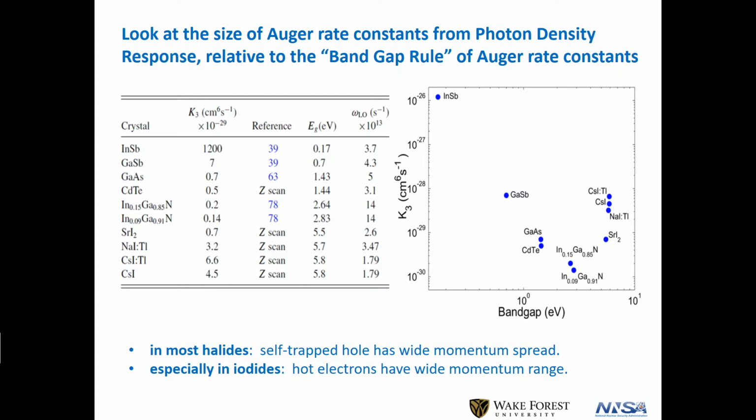So we wound up in the laser experiment measuring the band gap rule of Auger. I'll just skip over it. But from the semiconductor literature, because this is of great interest to people who make light-emitting diodes, you see the Auger rate goes down very steeply as a function of band gap, and it should go on forever. So in these 6 and 8 eV materials, the Auger should be entirely negligible by 6 or 8 orders of magnitude, but it's not. They jump up.